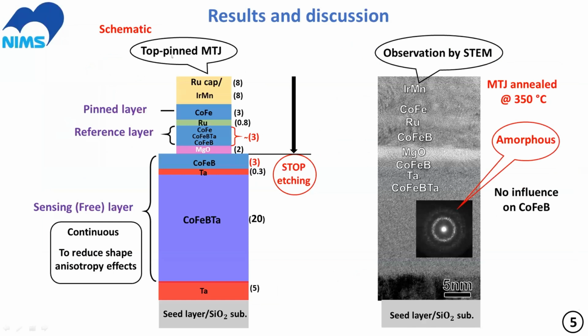As you can see here, I'm showing you the layer structure schematic that we developed at NIMS. It consists of 20 nanometer cobalt iron boron tantalum, and above it, cobalt iron boron. Then we can consider this as our sensing layer with very good soft magnetic characteristics.